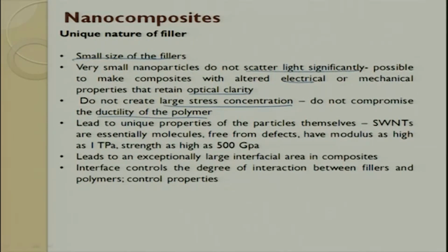This leads to a unique property of the particles themselves - single wall nanotubes are essentially molecules free from defects, having modulus as high as 1 terapascal and strength as high as 500 gigapascal, which is very difficult to get in a single material but is achieved in single wall nanotubes.